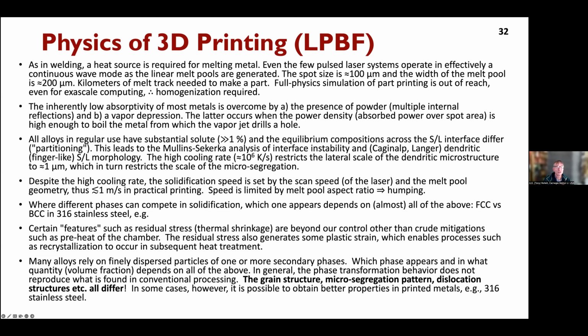Nevertheless, the typical cooling rates that you can get to there in the third bullet are on the order of 1 million degrees per second. And that means that the dendritic or columnar microstructure that you get has a characteristic length scale more like 1 micron, as opposed to the hundreds of microns that are typical in normal solidification. The solidification speed is basically set by the scan speed and also heavily influenced by the melt pool geometry. So it's typically less than a meter per second. We have some technical issues with going faster than that. Lots of interesting things there.